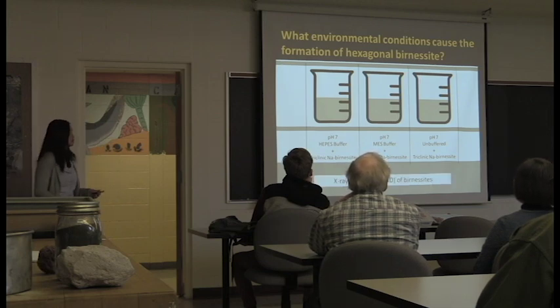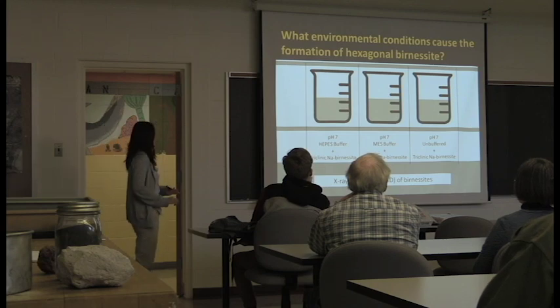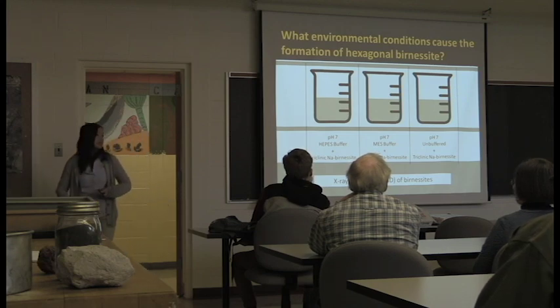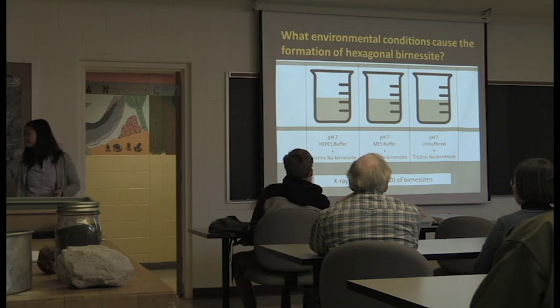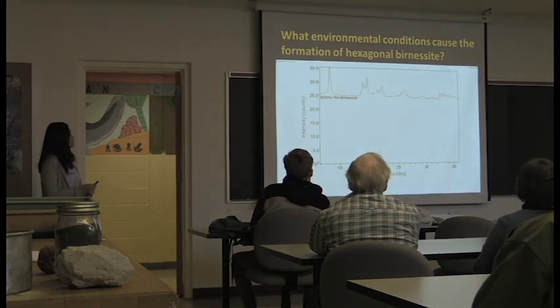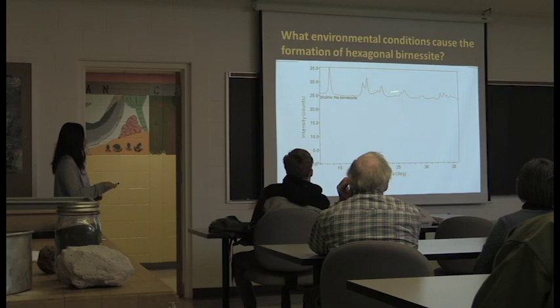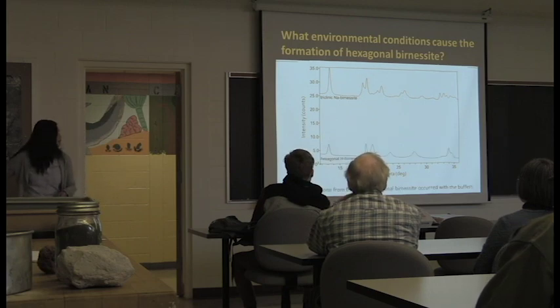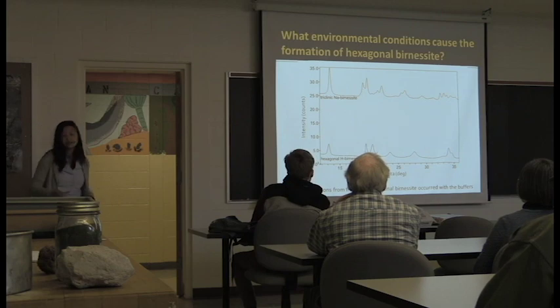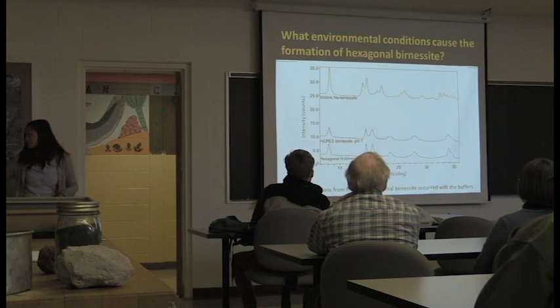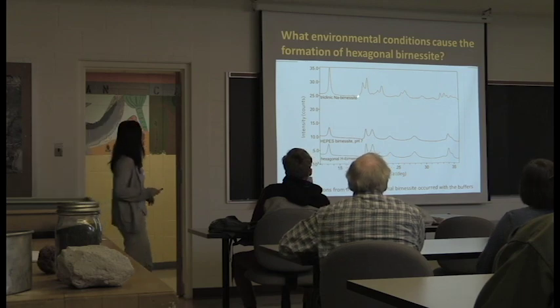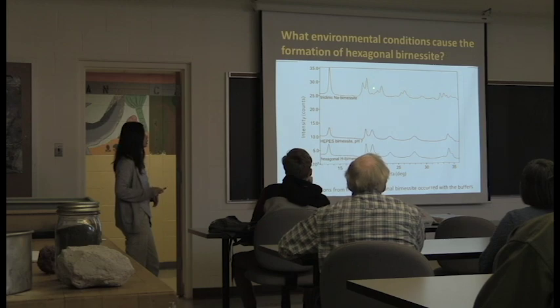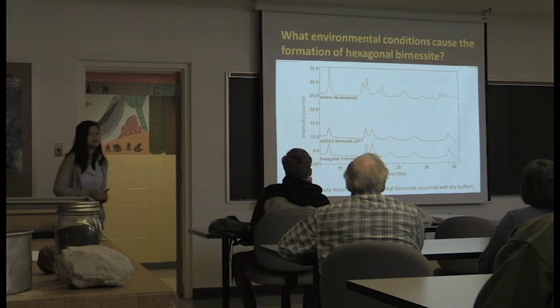What we did at the end of these experiments, these ran for 14 days, was we took the birnessites and we took an X-ray diffraction pattern of it. And this is, again, what a synthetic triclinic birnessite looks like, our idealized sample. And this is what a hexagonal birnessite looks like. So when we took this triclinic birnessite, when we put it in a HEPES buffered solution, we see that there are some changes in this region, and this material now matches hexagonal birnessite.